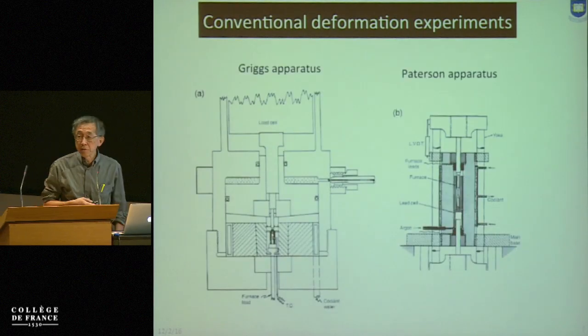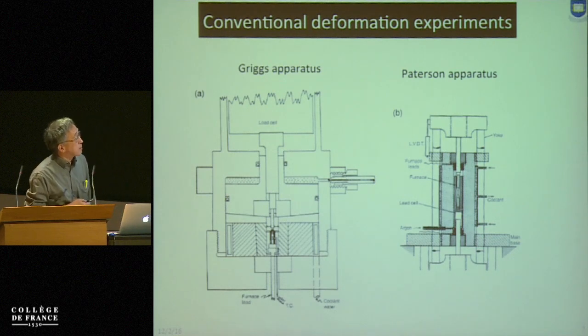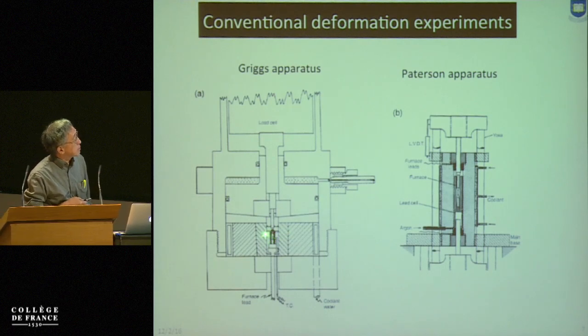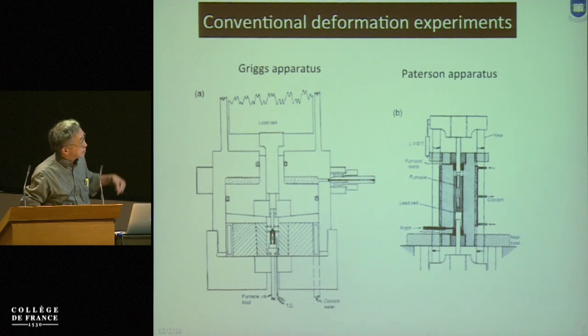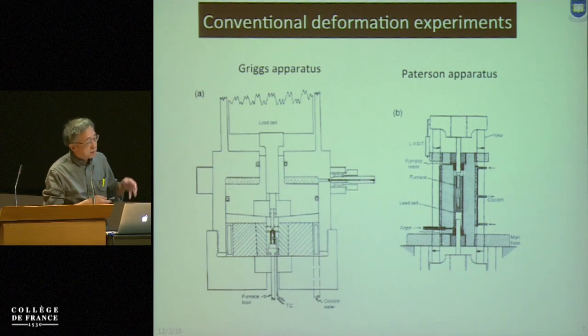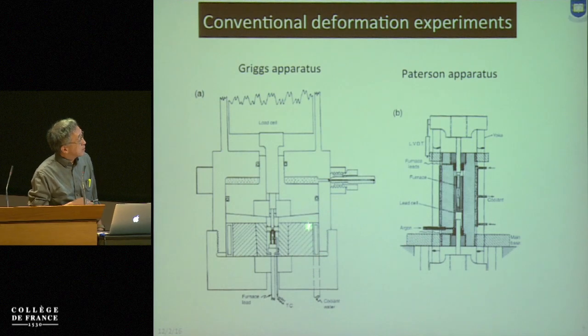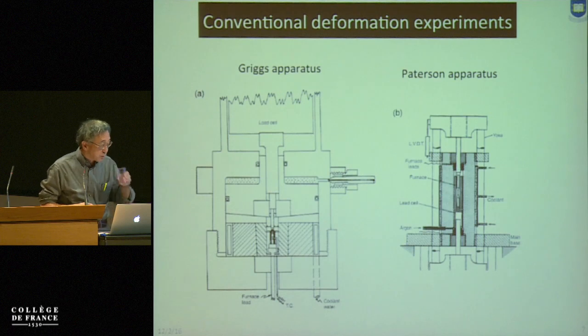Compared to this new technology, the classic apparatus, like the Griggs or Paterson, has your specimen set into the high pressure and temperature conditions. Then you apply load from an external actuator, and you measure the load. This is the stress measurement. Strain is also measured by an external gauge measuring the displacement of the top and bottom parts. The Paterson is the same thing. The load cell is inside, so it's high accuracy. However, the apparatus can go only to 0.3 GPa.